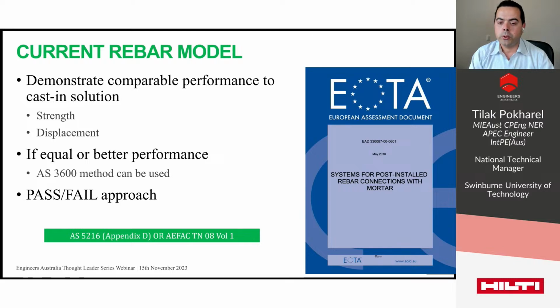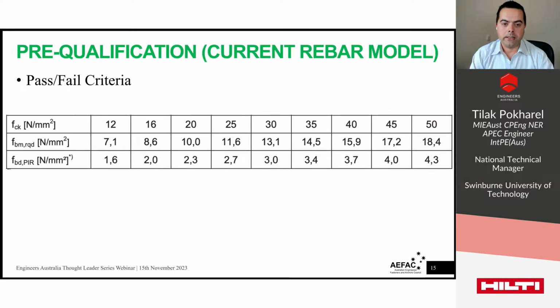That is, if the bond strength of the post-install reinforcing bar is higher than that of the cast-in rebar, we still have to use the bond strength of cast-in rebar. Okay, so I'll explain this with numbers in the next slide. Yeah, here it is. This is the table I took from the pre-qualification document EAD 330087. I put this table here to show how the design bond strength is determined in that pre-qualification method.